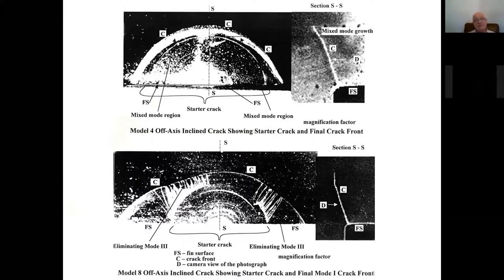As two examples, this is, let's say, the initial crack, the starter crack. Here you have some damage due to the blade, but in some cases you may need to strike with a hammer twice to grow a little bit more of the crack. And then the crack will start to propagate from the initial position, and this was the off-axis initial position. And then it will lean like this, and this is for the moment a mixed mode.